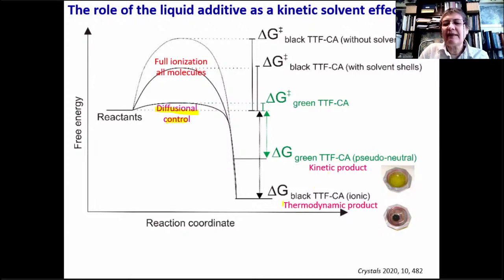But to prepare the thermodynamically most stable product, the ionic form, it appears that a polar solvent is necessary for this to happen, such as water and dimethyl sulfoxide. So these polar solvents may provide shells of solvent molecules so that the ionization of all molecules in that material becomes energetically possible. So it may actually promote the full ionization of all those molecules.